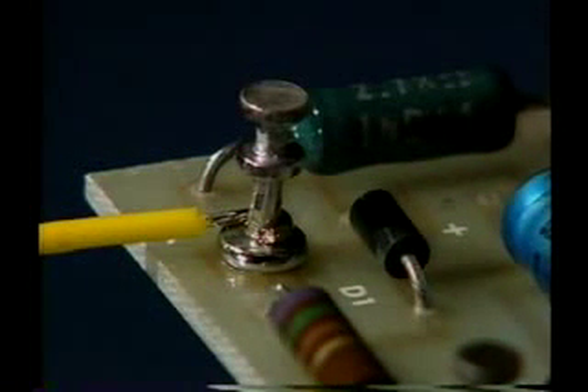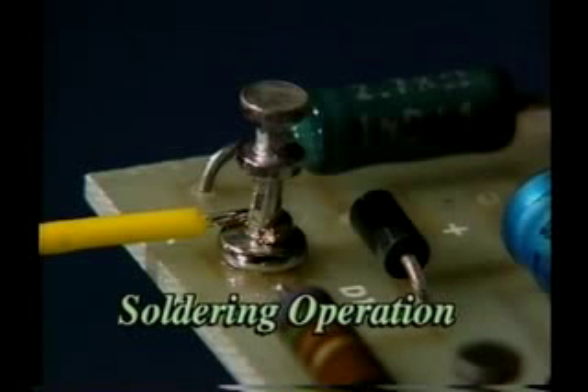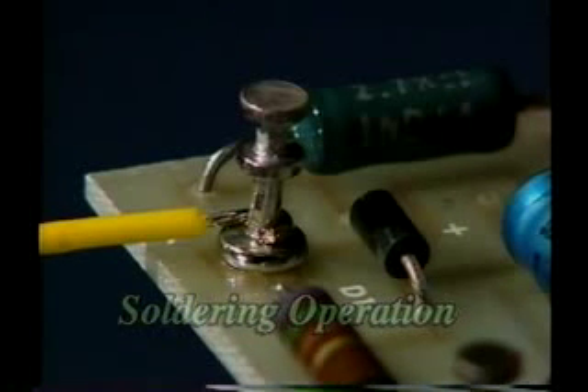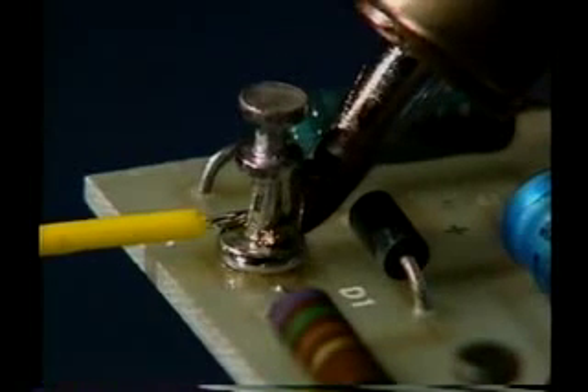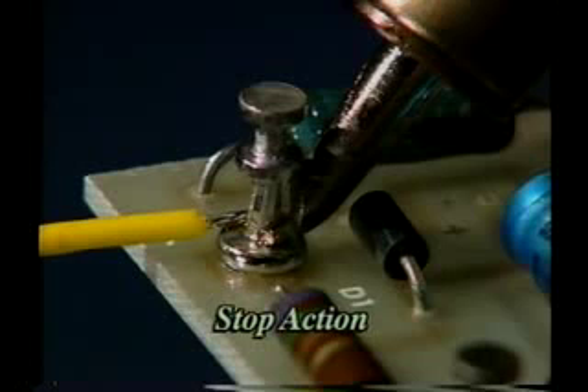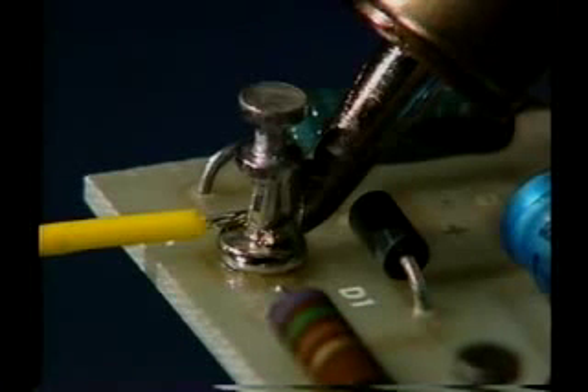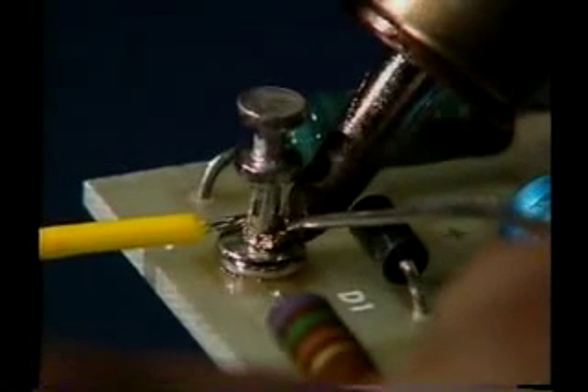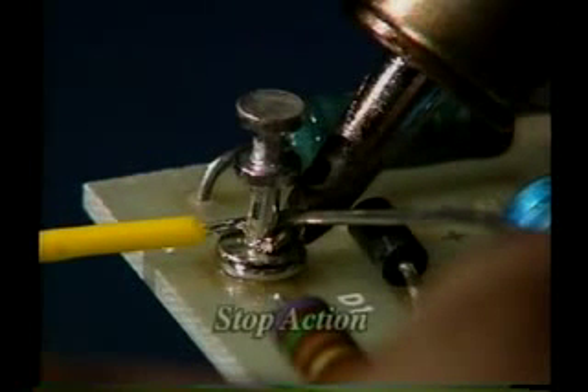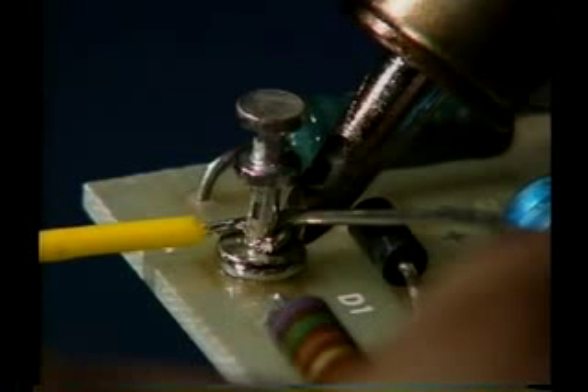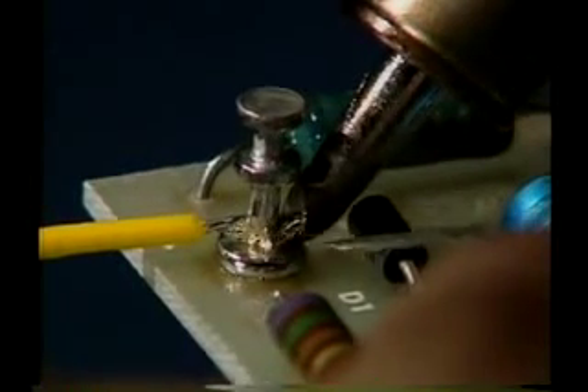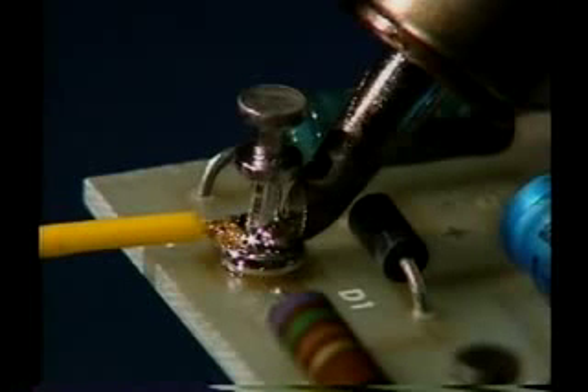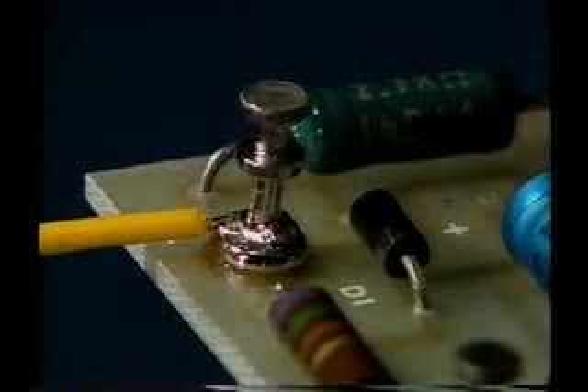Now let's take a look at the proper way of soldering turret terminals. The soldering operation consists of 4 basic steps. First, the iron should be placed in contact with the wire at the point of greatest thermal mass. This is called the contact point. The solder is added at the contact point to form a solder heat bridge. The purpose of the solder heat bridge is to transfer heat more rapidly to the solder fillet area. Additional solder is then applied on the opposite side of the point of contact to form the necessary solder fillet and removed. Then the iron is withdrawn at the same angle it was introduced to the joint.